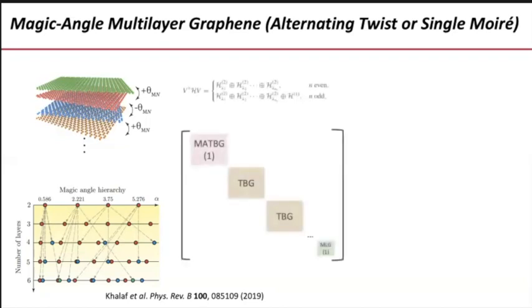So the system is such that if you rotate your Hamiltonian and choose the appropriate basis, you always get a block diagonal Hamiltonian where you always get a flat band, an analog of magic-angle twisted bilayer graphene. And then you have as many large-angle twisted bilayer graphene sectors, or blocks, as there are pairs of layers, even numbers of layers, in your system. And in addition, a monolayer graphene sector if you have an odd number of layers in total.